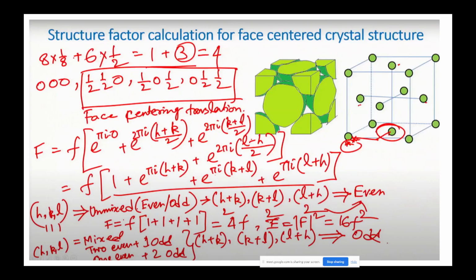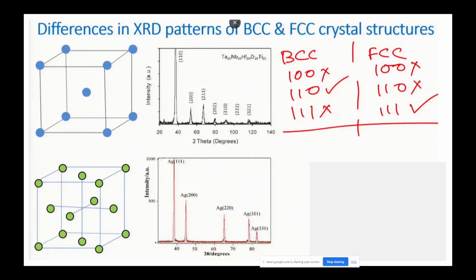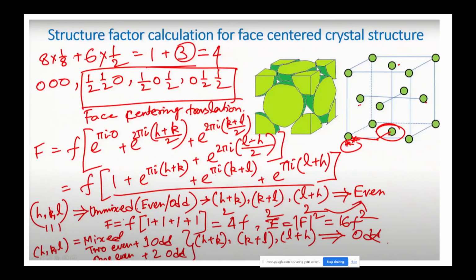Yes, so it is for the face center. So for the face center, when you calculate by the given formula, this is the structure factor. So HKL are unmixed and it is even or odd. So H plus K, K plus L, L plus H is even. When you calculate this, HKL will come mixed, two even plus one odd or one even plus two odd. Sorry, HKL are unmixed here because this is for FCC, right? So for FCC it is unmixed.